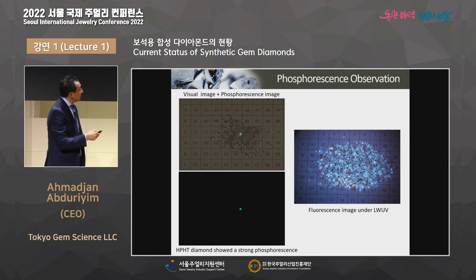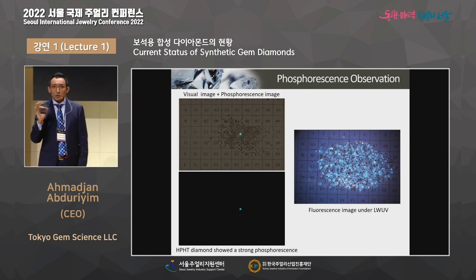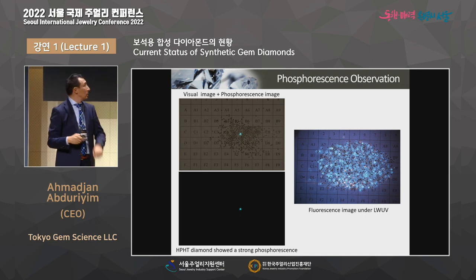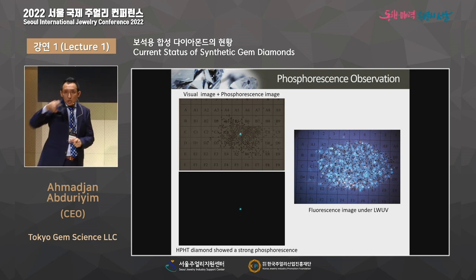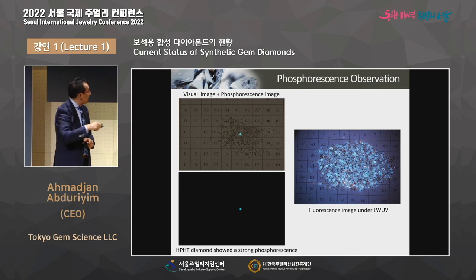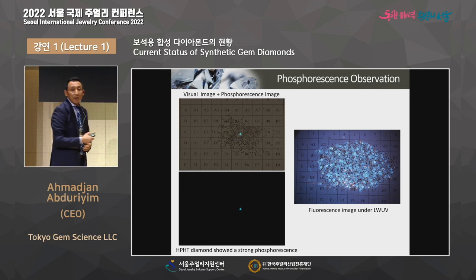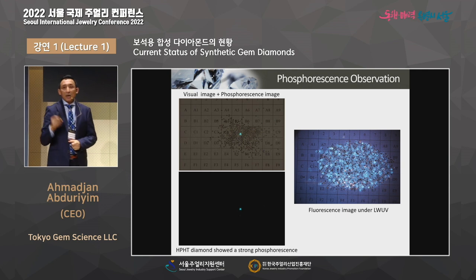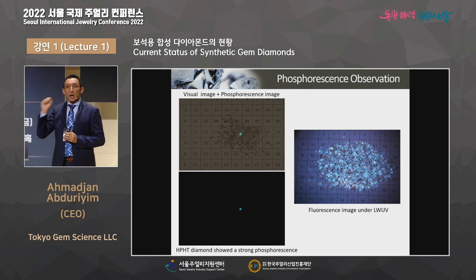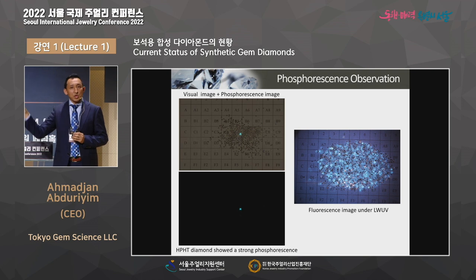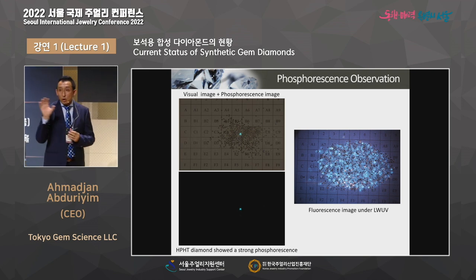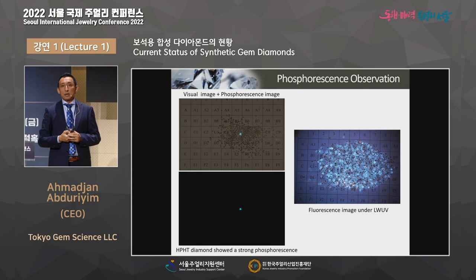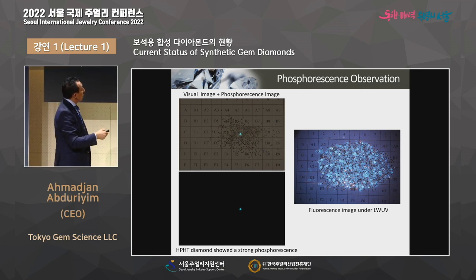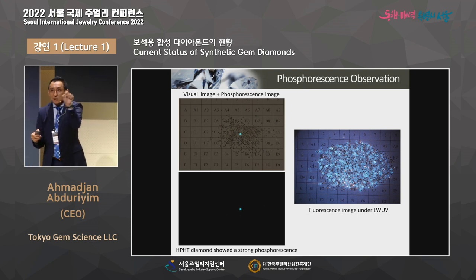However, the synthetic one from China doesn't show any fluorescence. That's good. And after you switch off the fluorescence UV light, then you will get the phosphorescence light from the diamond. I can say almost 99% of the synthetic diamonds from China show this kind of strong blue-green phosphorescence. That gives you one signal to pick it up. And this is an overlap with the visible photo, so you can find exactly where the synthetic is.